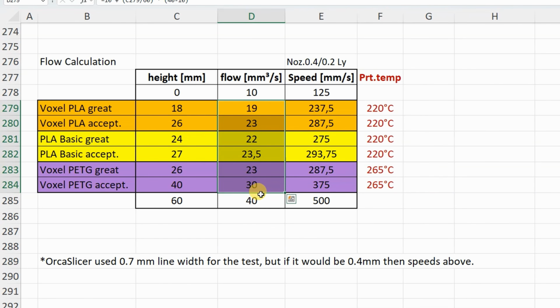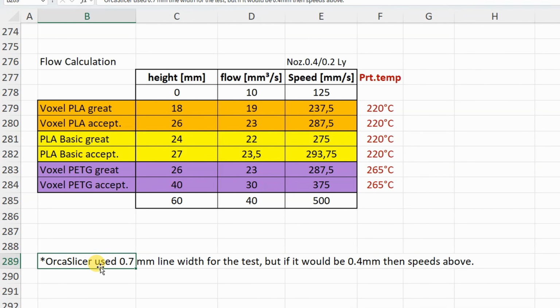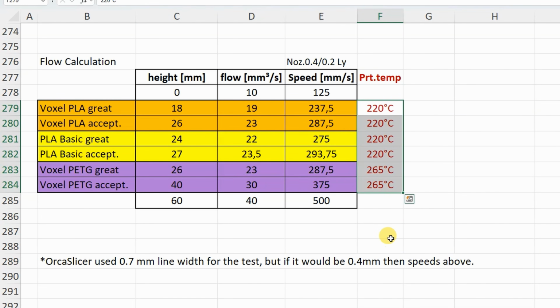And more or less for all three filaments, I will set, let's say, 20 cubic millimeters per second flow. That's almost in a safe zone. And these are those speeds if I calculate with 0.4 millimeter nozzle and 0.2 millimeter layer height. Don't be confused. Orca Slicer set the line width to 0.7 millimeters for the test. The reason for this is to reduce the speed, so it will not stress the printer with the speed, because this is the flow rate test. And these are the temperatures I use in this test.